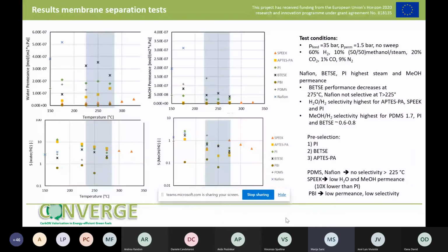These are the summary of the tests that we did for the Converge project in the separation mode. We used a feed pressure of 35 bar, which is a limitation of our installation. Permeate pressure was 1.5 bar, and no sweep was used. This is the composition of the gas that was used: permanent gases in combination with methanol and steam, which would typically represent the equilibrium coming out of the methanol reactor.